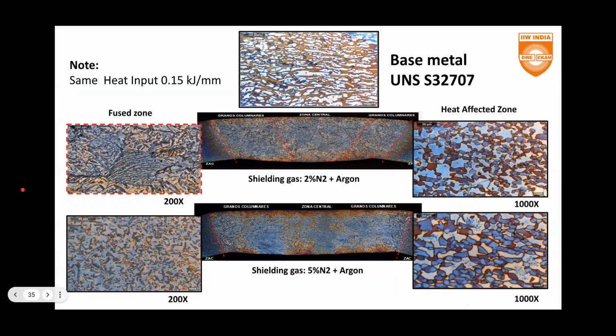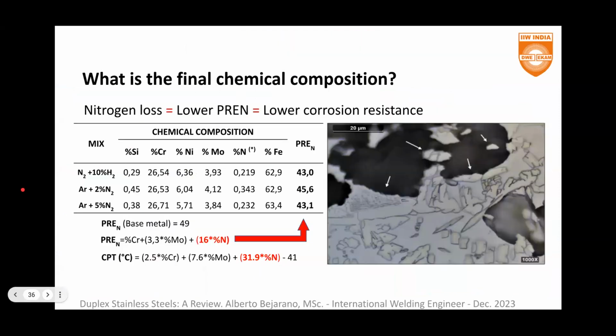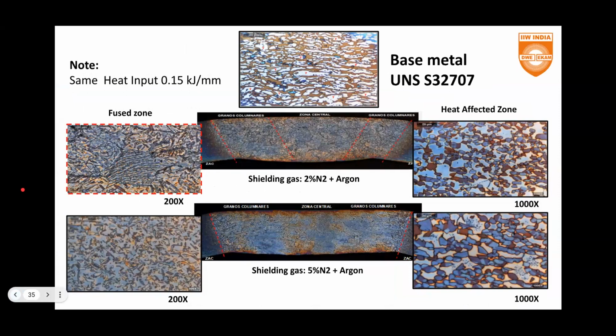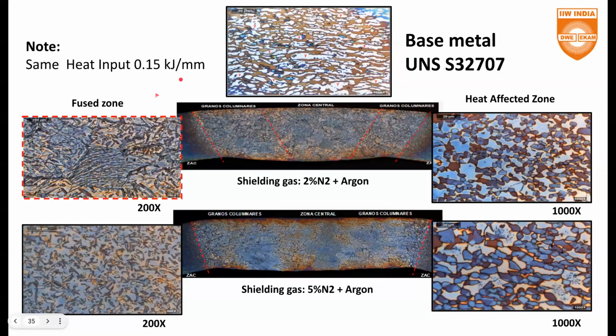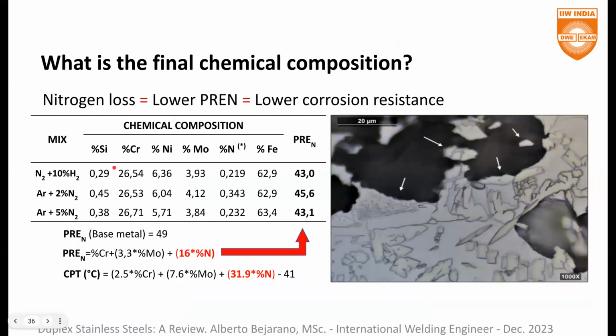duplex stainless steel. Okay, here we have a typical joint. Again, this is an hyper duplex. You can see the change produced by the heat, by the thermal cycle in our base metal. In the heat affected zone, we can see all these tiny grains here. And in the weld metal or the fusion zone, we have this kind of islands, which are very interesting, as we can see in a moment.